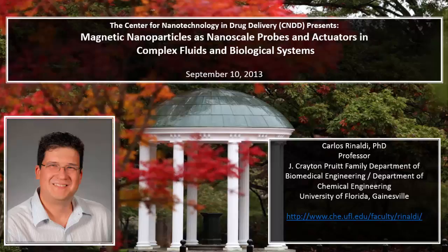As you might imagine, the dependence of each of these two mechanisms on magnetic properties of the material and on the surroundings is going to be different. And this can be quantified by these expressions for the characteristic relaxation time, which is the time it takes for the particles to align with the new field, for the Brownian and the Néel mechanism. What I want to point out is that in the case of Brownian particles, that is particles that are magnetically blocked at room temperature, the relaxation time depends on the hydrodynamic diameter of the particle and the viscosity of the surrounding fluid, or more generally, on the rotational hydrodynamic drag on the particle. And in the Néel mechanism, the time depends more on something called the magnetocrystalline anisotropy constant.